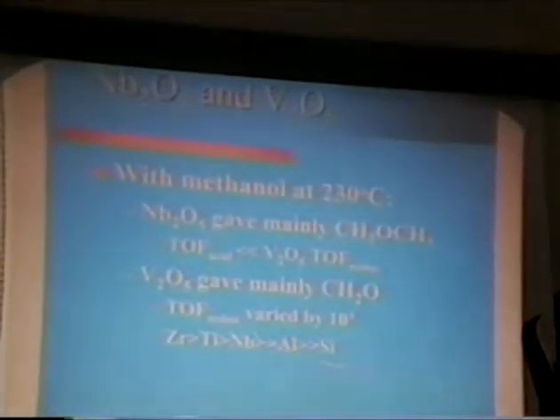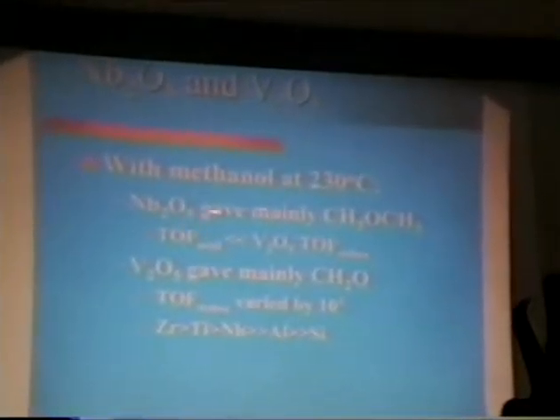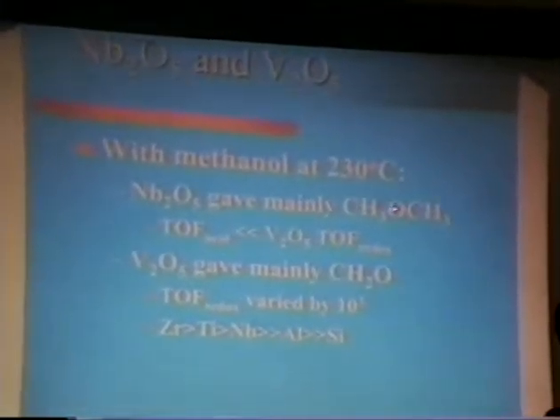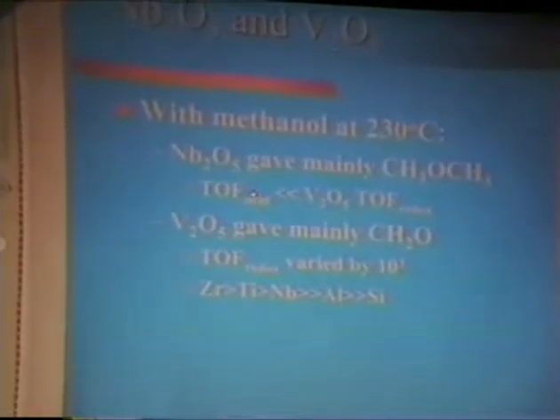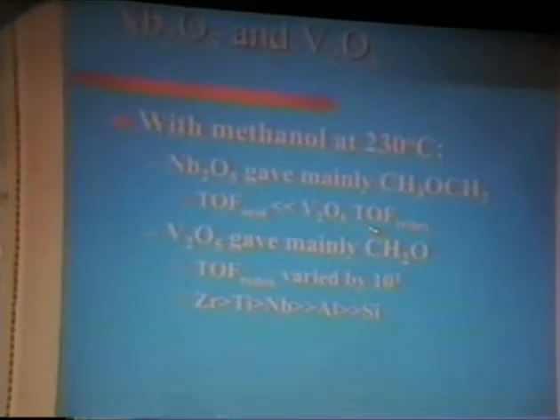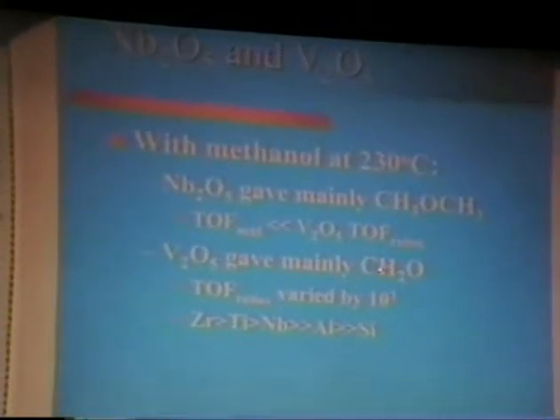In some of the work with methanol adsorption that he's done, we see, again, the acidity function that niobium gives mainly dimethyl ether, which is an acid function. The turnover frequency here is much less than the redox with vanadium, which gives mainly formaldehyde.